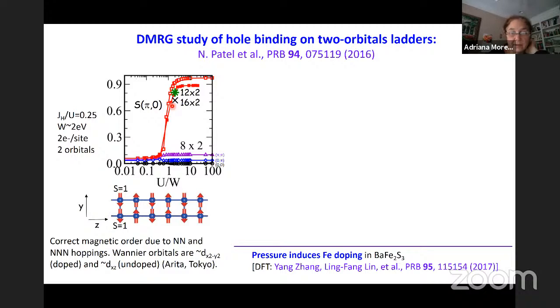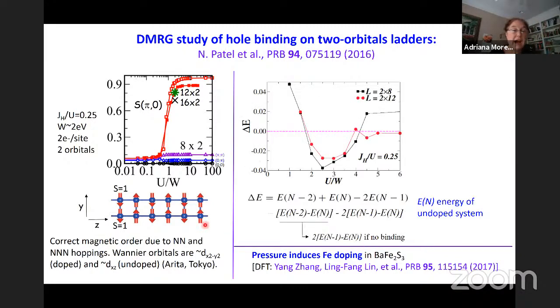We know superconductivity occurs with pressure, but DFT calculations by Zhang and Lin et al. demonstrated that pressure effectively induces doping in barium iron sulfide, iron doping. So we decided to study pairing in this system by looking at the difference in energy between putting two electrons together versus putting them separately.